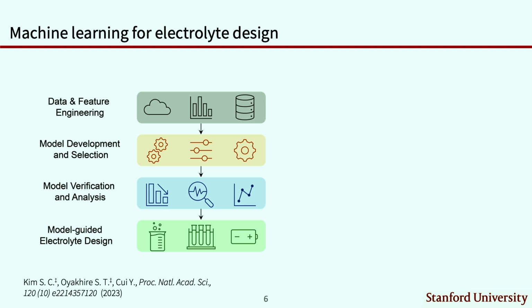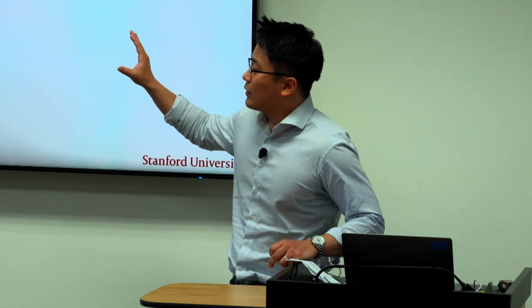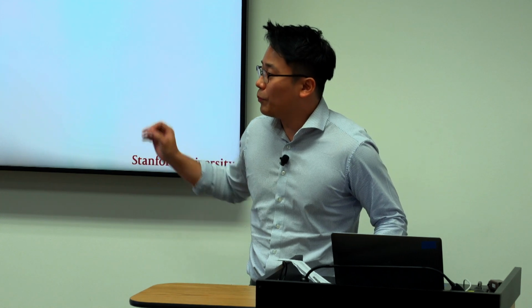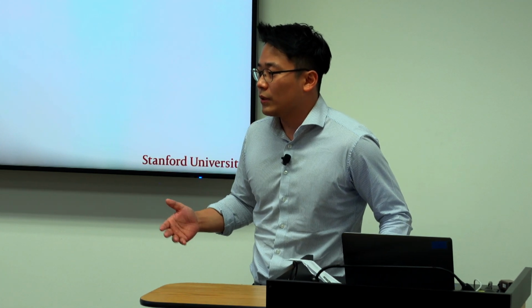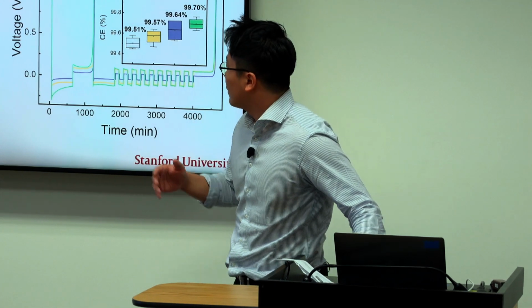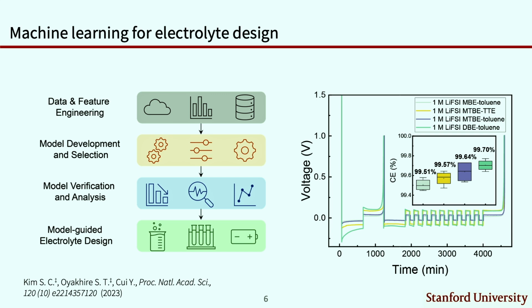Lastly, what I'll hit on is the machine learning study for electrolytes. Just to quickly show you the flow of what we did: there's significant buildup of data in the literature on different electrolytes and their performances. So we built a data set using these literature data and extracted key features from it. Then we built machine learning models based on many algorithms, verified these models, and extracted key insights, which led us back into the lab to design new electrolytes based on these insights and analysis from the machine learning algorithms. What we did at the end was develop high performance, high Coulombic efficiency electrolytes that were essentially driven by these machine learning models.